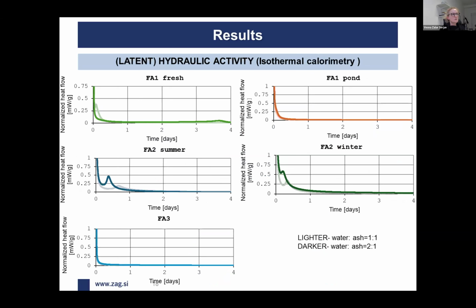At this step, we are aware that there are some phases that could potentially react only with water. So we tried to define the latent hydraulic activity of those ashes, meaning mixing the material only with water, without any additional additive which would increase this reaction. So we made pastes with each ash, and we made those pastes with two different water to ash ratios. The first one was 1:1, and the other one was 2:1.